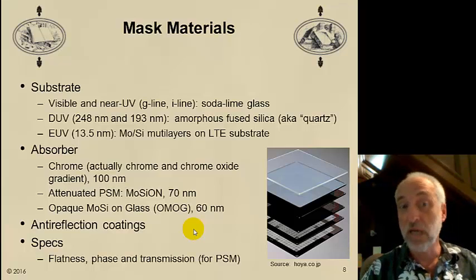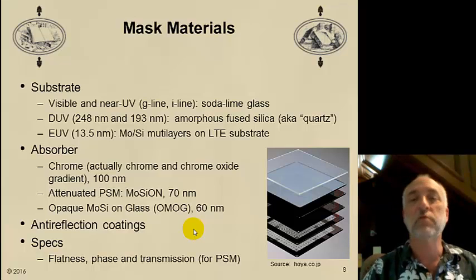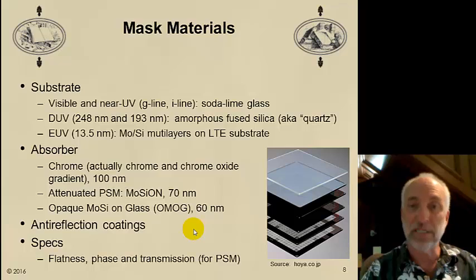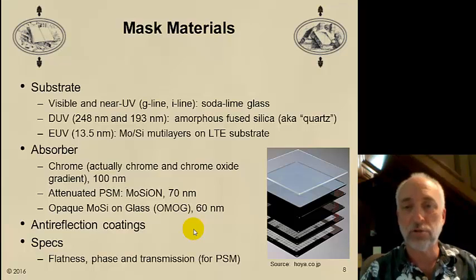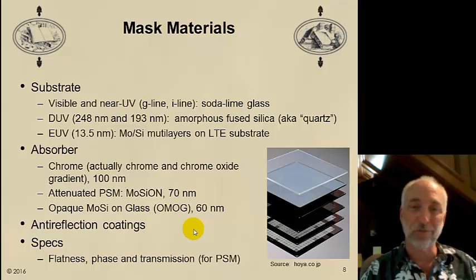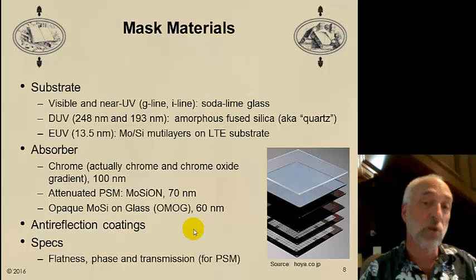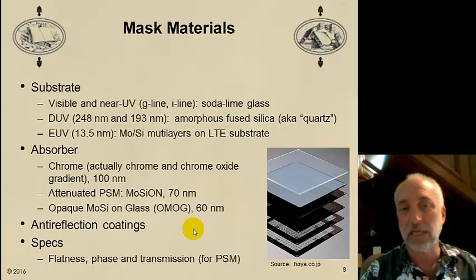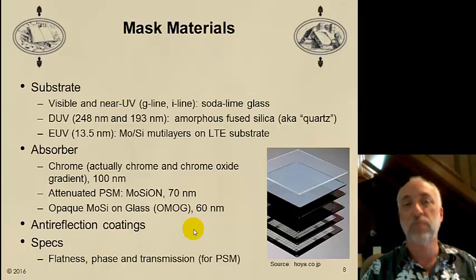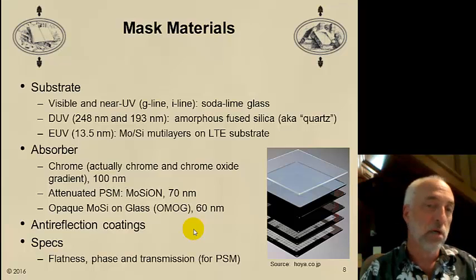For EUV, however, we'll talk about EUV masks in part 3, we actually have a reflective mask rather than a transmissive mask, and we have a non-transmissive low thermal expansion substrate, LTE substrate, with multi-layers of molybdenum and silicon, maybe 50, stacked up to make a reflector, make a mirror out of the EUV mask.